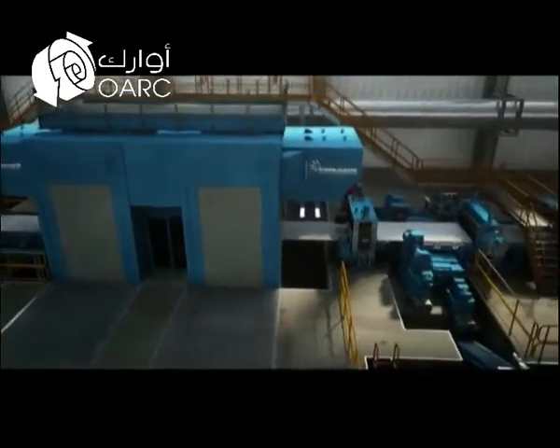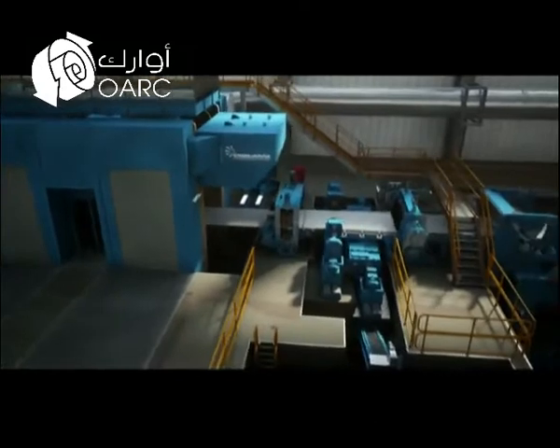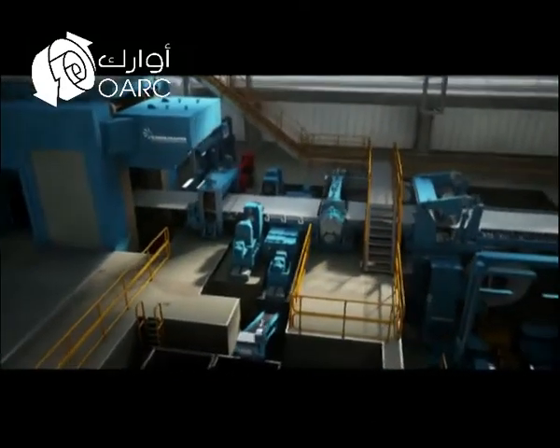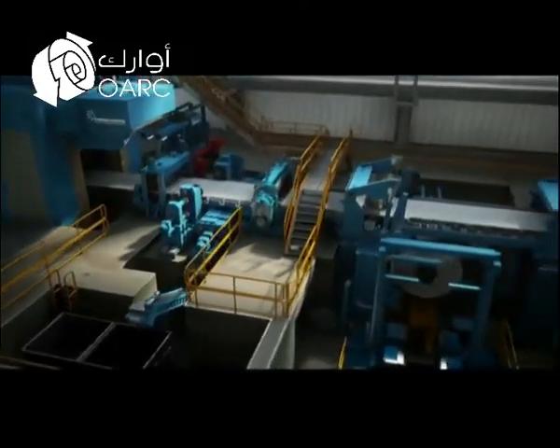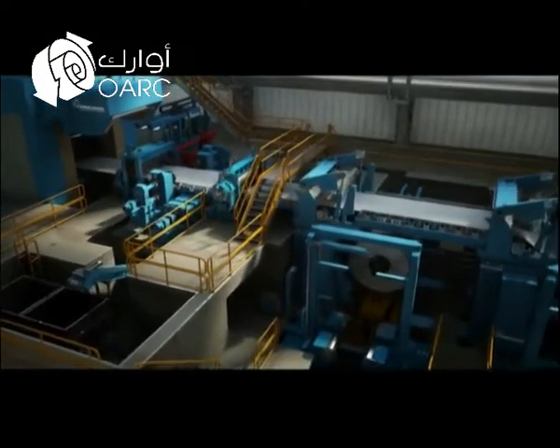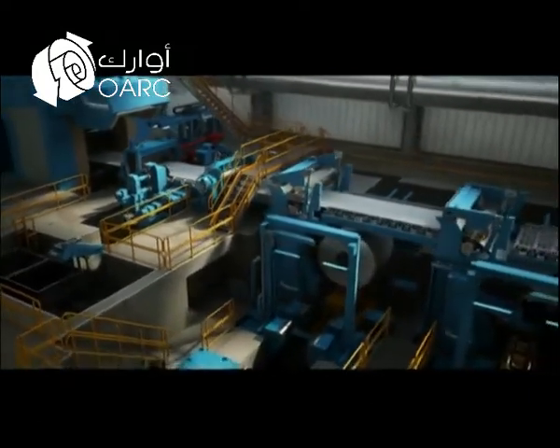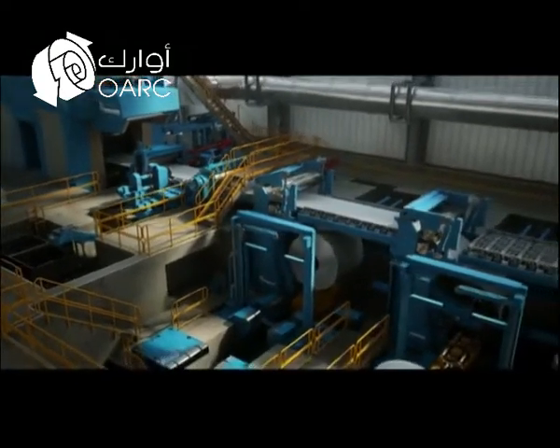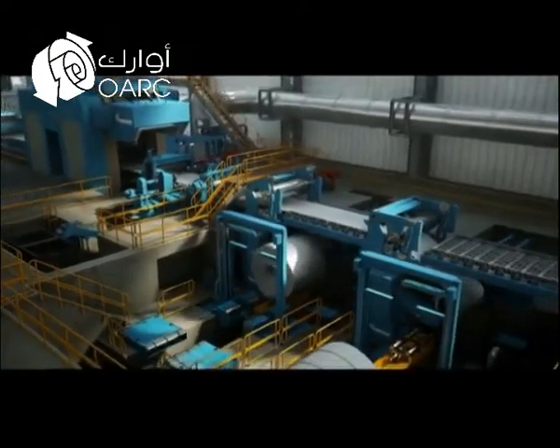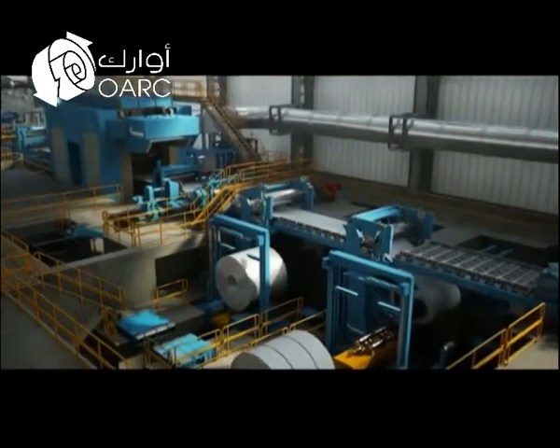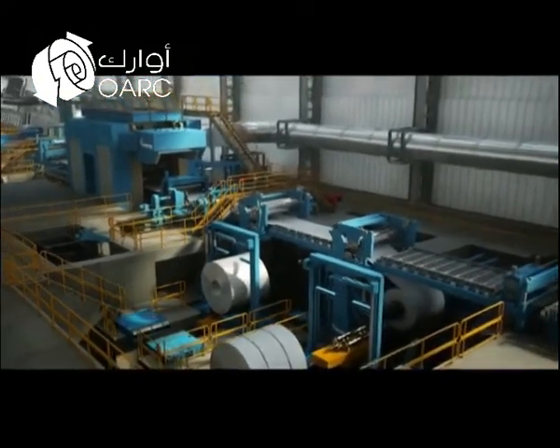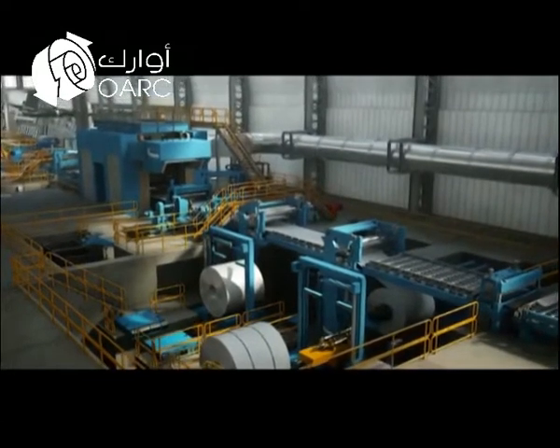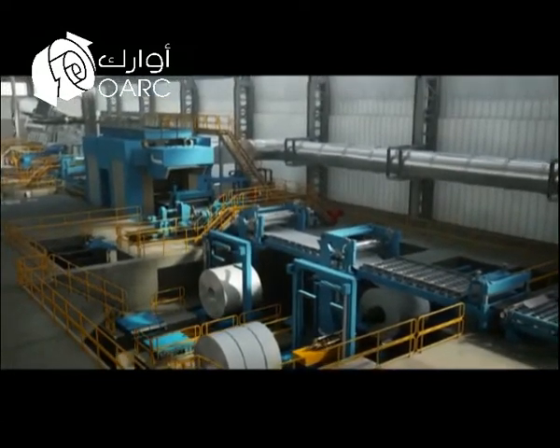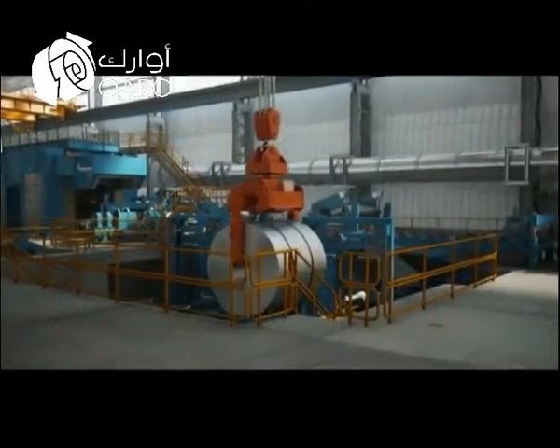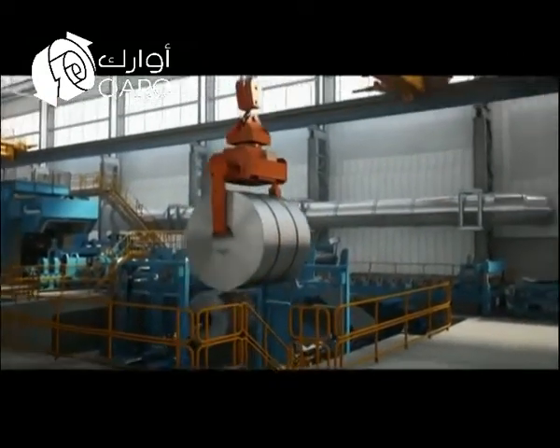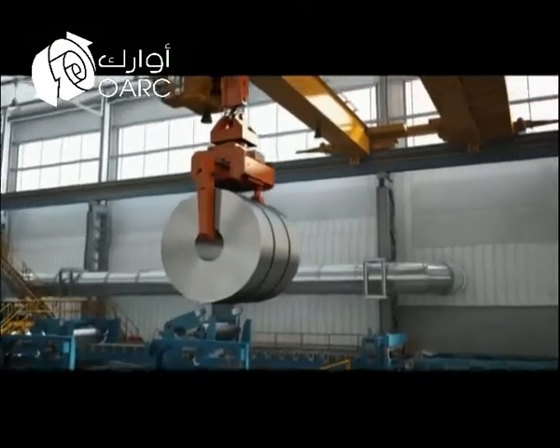At the exit of the second stand, the thickness and profile of the strip is measured using 2 X-ray gauges. When necessary, the edges of the strip can be trimmed during rolling to take out the edges defects or cracks. At the end of the coil, without stopping the casting and rolling process, the strip is divided using a flying shear to separate tail and head, and immediately a new coil is started, winding on the second down coiler mandrel. When a coil is completed, it is immediately transferred to a weighing and banding station, ready to be removed by the overhead crane.